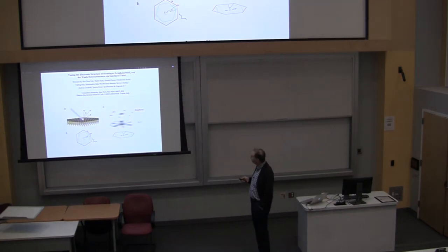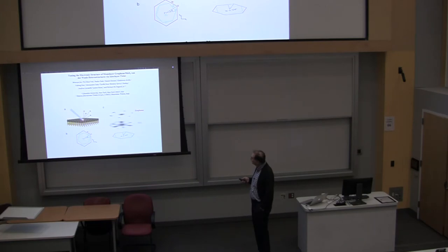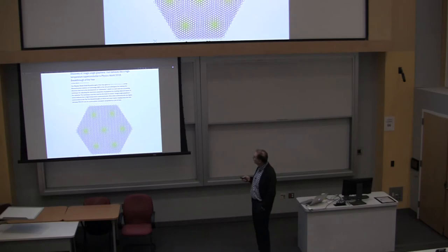What people have been doing is stacking, in this case, graphene on a molybdenum disulfide. And there's a twist angle that you can also measure, right? We learned a lot about twist angles this year because of that big discovery. You can do all kinds of things like spectroscopy. There was a big discovery named Physics World's Breakthrough of the Year, where Pablo Jarillo-Herrero at MIT and his group discovered magic angle graphene, and was able to go from basically being a Mott insulator to a superconductor with a twist angle. That was a very nice result, and there's a lot of activity going on in that area.